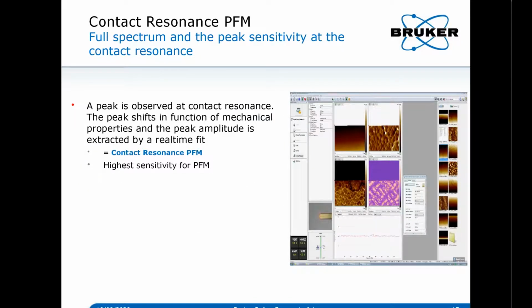So how can we use it specifically for PFM? We mentioned earlier many times that the piezoelectric response, especially from thin films or 2D materials, is very weak. Even if we use the lock-in amplifier, use the AC drive signal and detect the AC deformation, it may not be enough for some applications. So people use the resonance enhanced method to enhance the signal of this kind of deformation. But at different locations on the material, the roughness can be different. And the material itself can also be not that homogeneous, which all give you the result that at each pixel or each location, the tip interaction with your sample can be quite different.